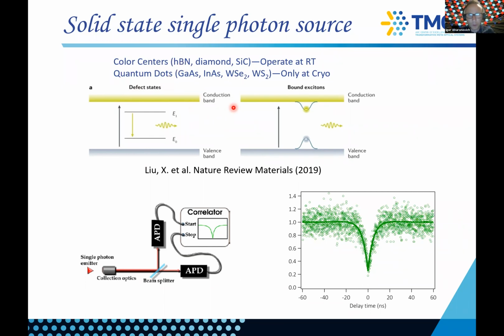And this is fundamentally a bit different than what we call exciton transitions or localized excitons. And these are basically very low energy traps just above or just below the valence or the conduction band. And these systems also can be isolated. So of course, the most common system is your epitaxial quantum dots. And more recently, with the emergence of 2D materials, you have the trapped excitons in WSe2 and WS2, et cetera, et cetera. And so the fundamental difference between the two is really the operation temperature. Those systems operate mostly at cryogenic temperatures, and the defect states operate at room temperature.